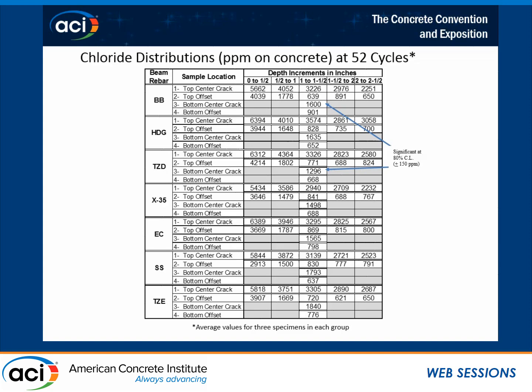And you can see chloride is slowly coming through the samples, even away from the crack. But this is also 2 years of heavy ponding, so it's a very severe condition. If we look at most of these bars, they did not show any difference at the bottom offset.